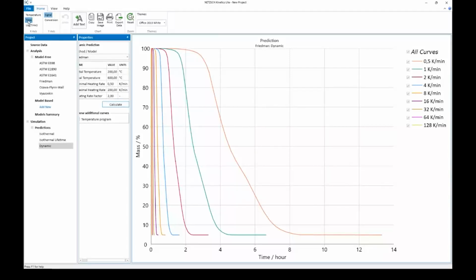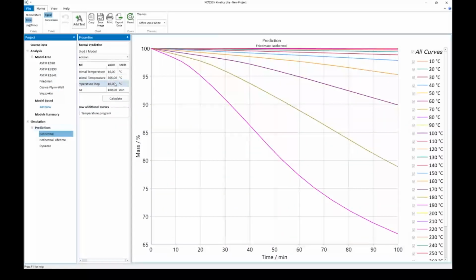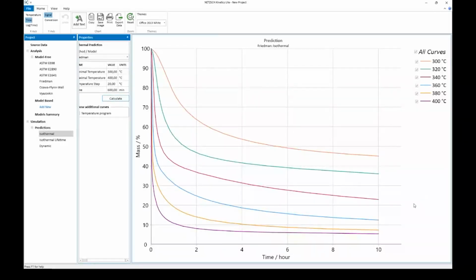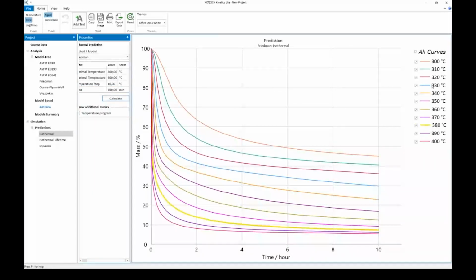Now we will make, for example, initial temperatures between 300 and 400, isothermal, from 300 to 400 with 20 degrees between them, and we will wait, for example, 10 hours. Here is a result for 10 hours for isothermal decomposition at different temperatures. We can make a step, for example, 10 degrees C, and we have for each 10 degrees C for 300, 310, 320, and so on. That was isothermal.